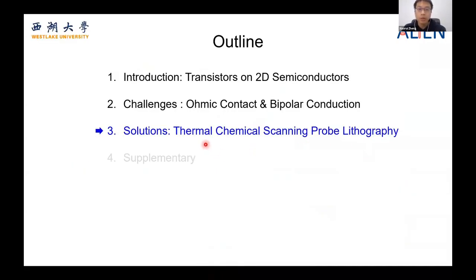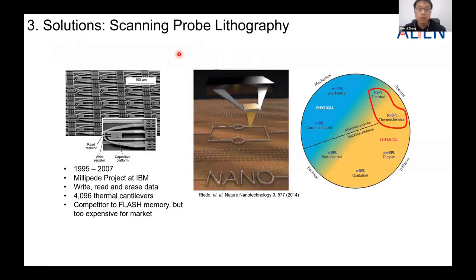Okay, for our solution, we propose to use the thermochemical scanning probe lithography technique to improve the quality of the contacts and also to achieve bipolar conduction on MoS2 transistors. A little bit of introduction to scanning probe lithography. It was developed in 1995 in the Millipede project at IBM. The idea is to introduce a resistor at the end of the cantilever, and by flowing a current, the resistor accumulates heat that can be transmitted into the tip of the cantilever.